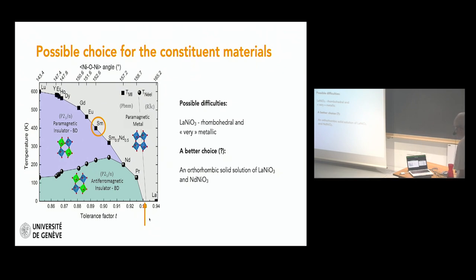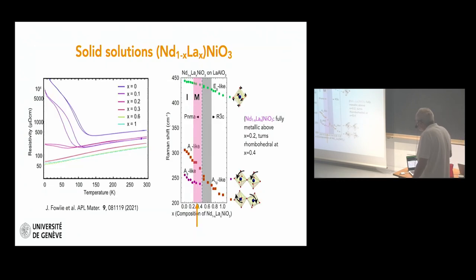And so we made a solid solution of lanthanum nickelate and neodymium nickelate. And there we profited from some previous work in the group by Jennifer Fowley, who studied the solid solution of neodymium lanthanum nickelate. And you see here Raman measurements which allow the structure to be determined. We know from these measurements that up to this point we are in the orthorhombic phase, and we turn rhombohedral here. And there is a part of this phase diagram, the pink region here, where the system is orthorhombic and metallic, and we decided to target this.